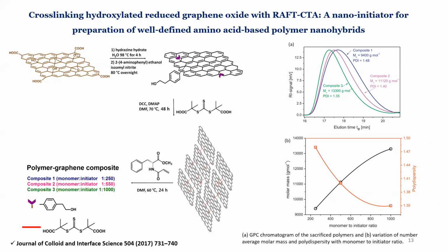Further, I decided to see if we could have control over the polymerization if we started polymerization from in between the sheets. So I designed this RAFT agent with a double functionality, attached cross-linked graphene sheets with this, and went with an amino acid-based monomer, which is hydrophobic. We did a polymerization with 3 different monomer to initiator ratios. As you can see on the right, the polydispersity index was close to 1, and we had good control over the polymerization. So we could really go with this method, we could obtain well-controlled RAFT polymerization.